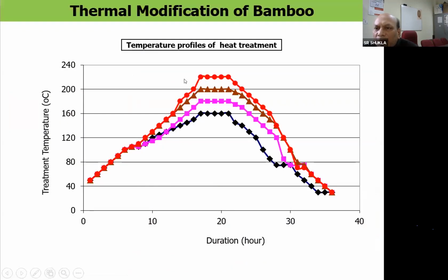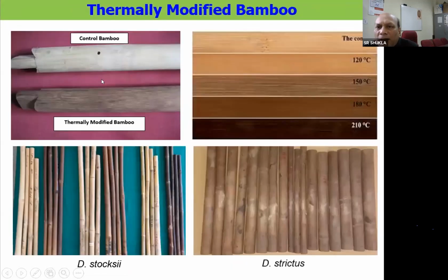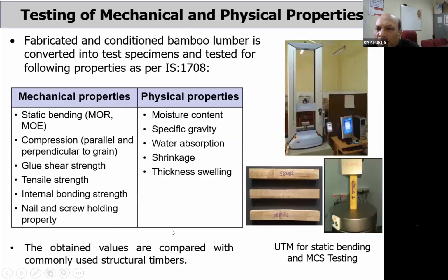And these are the different temperature profiles which we have been using for treatment of bamboo modification. Here we can see the colors of the bamboo, which is this is control bamboo and this is the thermally modified bamboo. So you can see the changes in the color. This color can be controlled based on the processing parameters. This is Dendrocalamus strictus bamboo which has been converted, and this is Dendrocalamus, untreated and treated bamboo at different temperatures. The higher the temperature, the darker the brownish color, and the properties will also change accordingly.